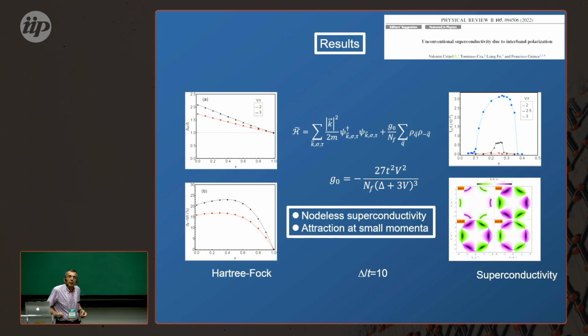That's what I'm going to talk about. What we found is similar to, let me see if this shows, no. This is that. The order parameter is in the lower right corner. F is what we call F wave, which is similar to the order parameter Andrey Chubukov was talking about this morning, which means you have two valleys, two Fermi pockets, and the order parameter changes sign when you move from one pocket to the next.